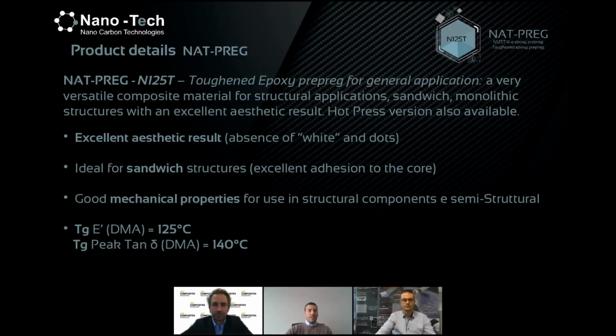Then we go to our core business, that is the production and sales of prepreg. We developed a range of prepreg from, let's say, more general purpose to very special products such as Cpreg, which we will see later. Here we can see at a glance the NI25T, a toughened epoxy matrix for general application with very good structural properties and very good aesthetic result, so it can also be used for aesthetic components. The material has a Tg of 125 degrees and can also be used for sandwich components and monolithic structures.